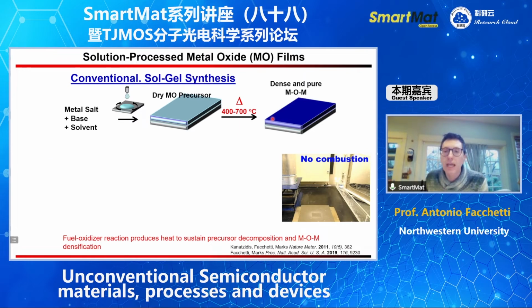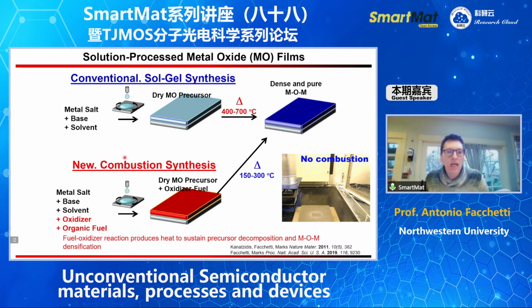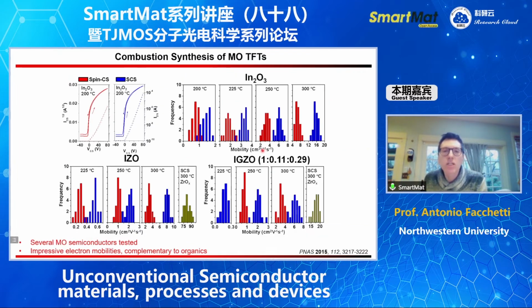And we have shown that we can prepare metal oxide films using a technique called combustion synthesis, which allows us to produce metal oxide films that are very, very dense at low temperature. This is not so important. What is important is that by using combustion synthesis, we made many different types of TFT processed at very different temperatures in many different ways. What is very important, and I want to remind you, is that metal oxides are great electron transporting materials. Instead, the best organics are typically hole transporting materials.